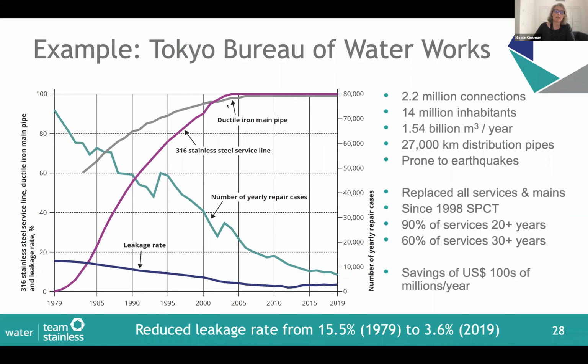And so in addition to replacing all service mains, of course, they also divided the city into DMAs. They increased leakage detection and did faster leakage repair. And all of these measures have led to this reduced leakage from 15.5% originally to about 3.6% right now. And they're holding around this 3 to 4% for over 10 years now in Tokyo. What's also very important for cost savings is the number of leakage repairs, and they went from some 70,000 to around 7,000 per year, as I mentioned previously.